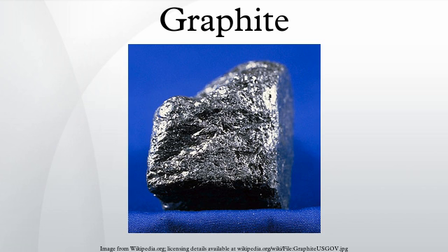Intercalated graphite. Graphite forms intercalation compounds with some metals and small molecules. In these compounds, the host molecule or atom gets sandwiched between the graphite layers, resulting in a type of compounds with variable stoichiometry. A prominent example of an intercalation compound is potassium graphite, denoted by the formula KC8. Graphite intercalation compounds are superconductors. The highest transition temperature Tc equals 11.5 kelvins is achieved in CaC6, and it further increases under applied pressure.